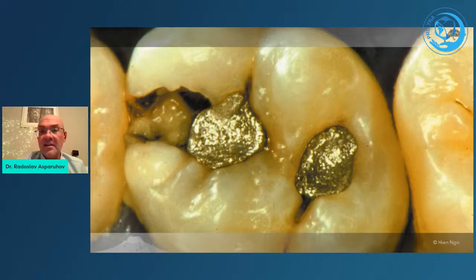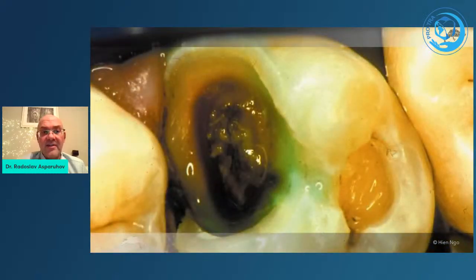So if you take a look at this case, there is an acute caries after removal of the old amalgam. You can see a very, very deep cavity that, if we do a complete excavation, we are going to definitely need to do a root canal treatment. So take a look at the borders of the preparation. The peripheral zone is completely sealed, completely clean, so we can seal it from the outside, while the infected area is covered with high fluoride releasing glass ionomer. In this case, it's Fuji Triage. This method is called internal remineralization, and we are counting on the high level of fluoride release to this affected dentin.